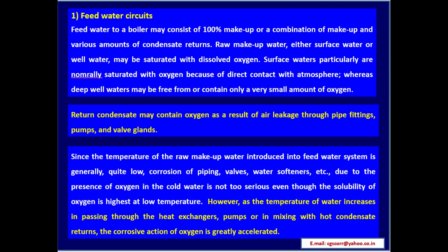Feed water circuits. Feed water to a boiler may consist of 100% makeup or a combination of makeup and various amounts of condensate returns. Raw makeup water, either surface water or well water, may be saturated with dissolved oxygen. Surface waters particularly are normally saturated with oxygen because of direct contact with the atmosphere, whereas deep well waters may be free from or contain only a very small amount of oxygen. Returned condensate may contain oxygen as a result of air leakage through pipe fittings, pumps, valve glands.